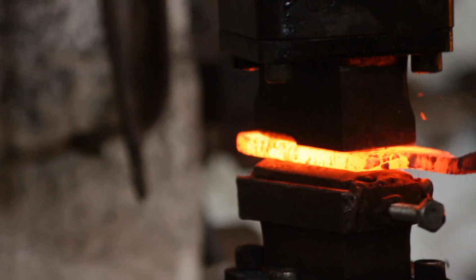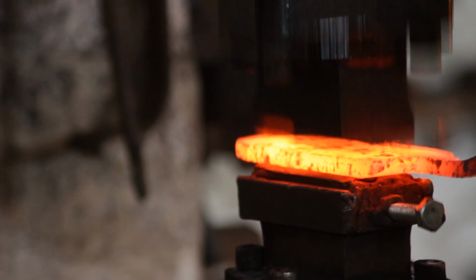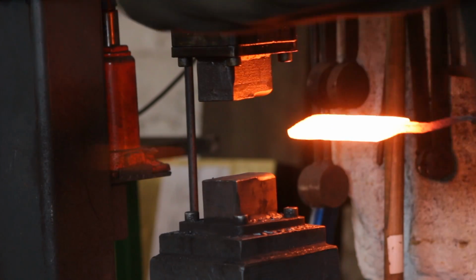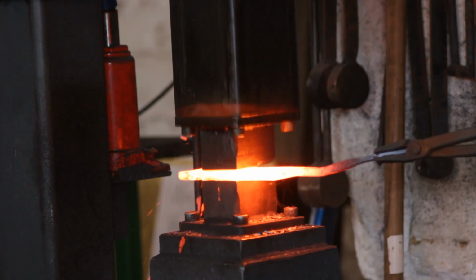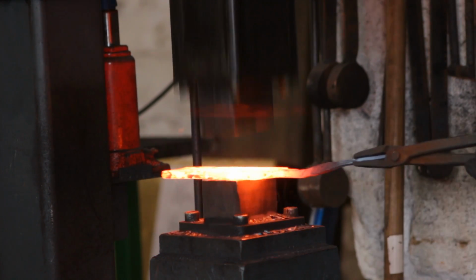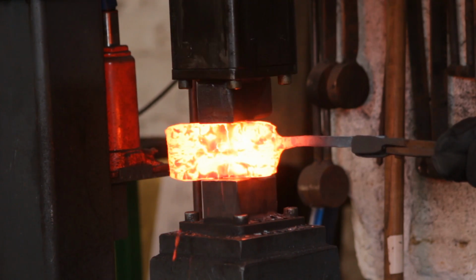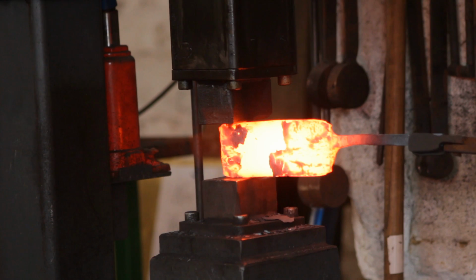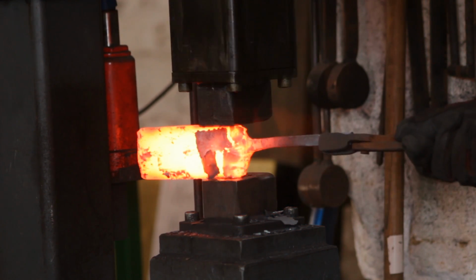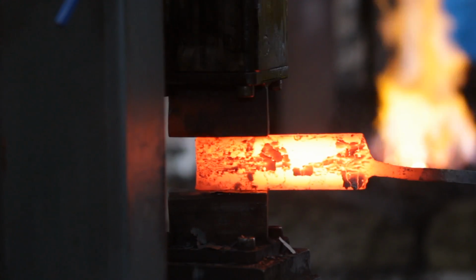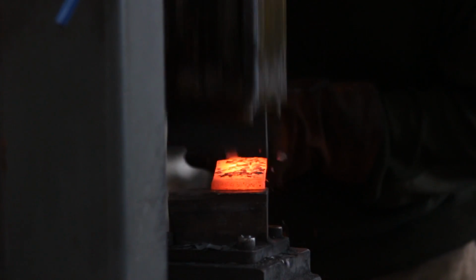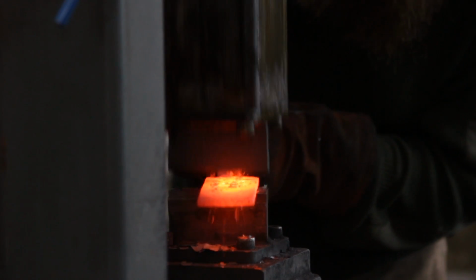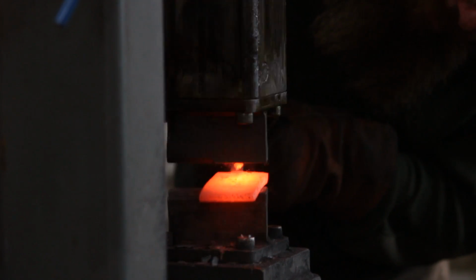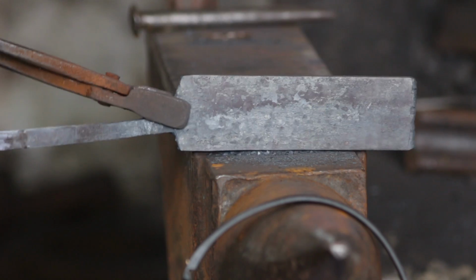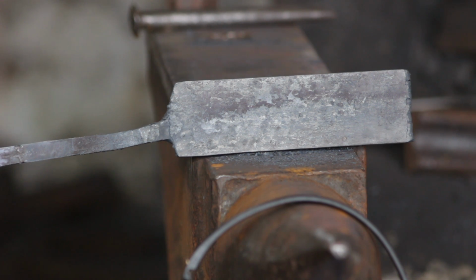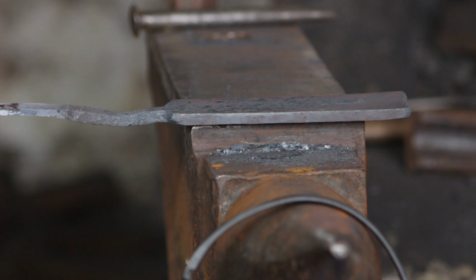However, the final thickness will be 2mm, so I am leaving the billet thickness as 5 to 6mm, and that will give me some grinding work to do, but it will ensure that I have a nice accurate socket. So once I've spread it out to 60mm, I will then bring it back down to 55mm. Under the power hammer again, it's much quicker like this. And then just make sure it's even all the way around. And here we have the billet prepared to be turned into a socket. It's nice even thickness, nice even section, and it is refined iron.